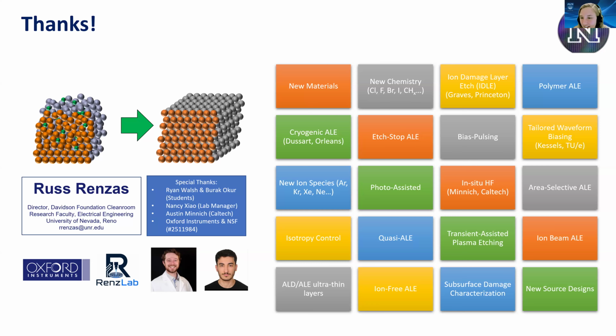So then let's see. Jiho Yoon said, "Thank you so much for the nice talk. I have a question about tantalum ALE. As far as I understand, the ALE etch per cycle will vary depending on crystalline orientation of the material, silicon 100 versus silicon 111 due to surface binding, energy packing, etc. Any comment on tantalum? Thickness of the film, can it be grown alpha beta? Do you see a difference in the etch per cycle?"